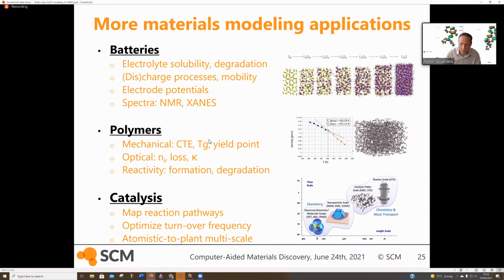So when you start to discharge your classical lithium ion, lithium sulfur battery, the lithium starts to intercalate into the sulfur electrode, and that leads to stress. And you can model this by doing grand canonical Monte Carlo simulations with ReaxFF. And then during the discharge process, you can see the expansion, and you can also see the reduction of the chemical potential that corresponds to a reduction in the voltage. So let's see what that looks like.